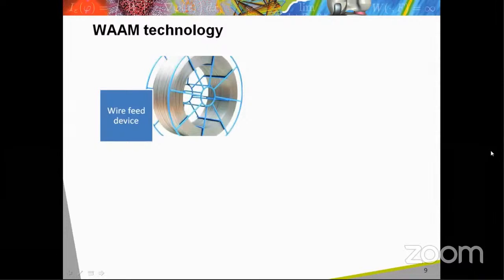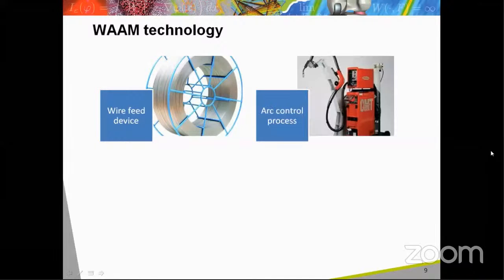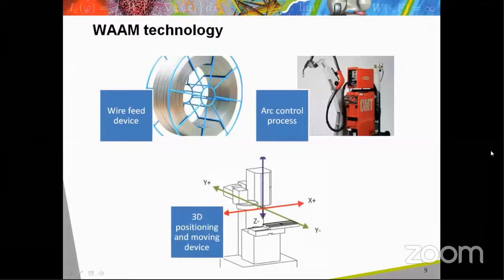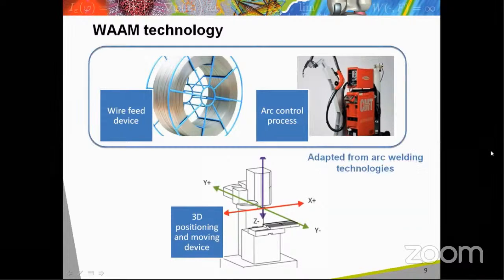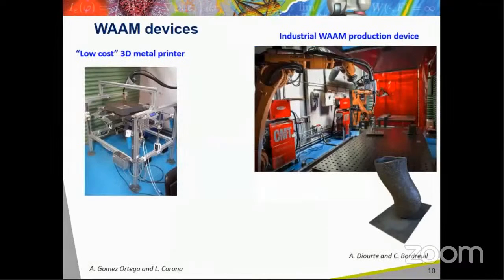The WAAM technology is composed of three main elements. The wire feed device that allows compensating the melting and deposit of the wire end, the arc control process, and finally, the 3D positioning or moving device of the deposit head. As was said previously, the wire feed device and the arc control process in the WAAM process are similar to those used on arc welding processes. One can see on this picture two kinds of WAAM devices corresponding to two kinds of 3D moving solutions.